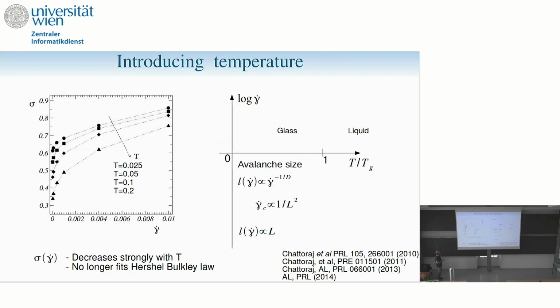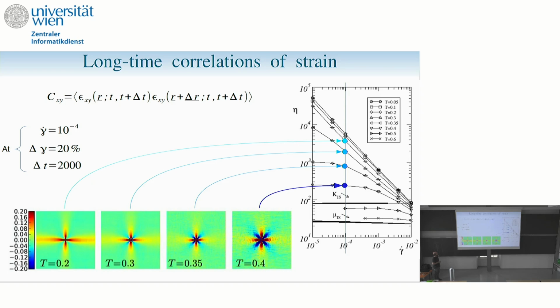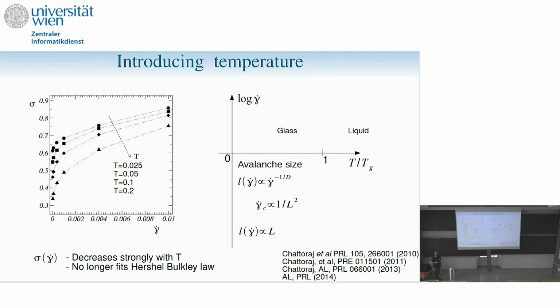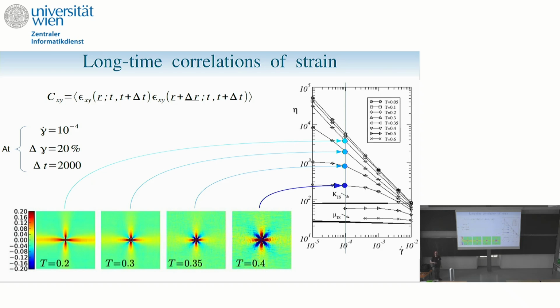There is one thing I would like to draw your attention to. I will maybe skip some of the details, but if you look at the stress, here I'm looking at the stress versus the strain. I told you here that the avalanche behavior extends up very high in the liquid, up in the non-Newtonian regime. Now, if you look at the stress, you see something different. The stress tells you another story. The stress tells you that a very small change of temperature causes a very sharp drop in stress, much before you reach the liquid. Here I'm looking at the temperatures 0.025, 0.05, 0.1, 0.2. 0.2 is near the Tg, again it's 0.25, something like that. So here you have a very rapid drop of stress at low temperature, but the avalanche pattern doesn't seem to depend on temperature in the low temperature range.